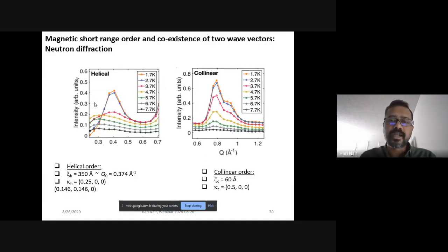So this is a clearer depiction of those two different wave vectors. A wave vector would only indicate what type of ordering you have. If you have a helical ordering, that corresponds to a Q0, which is the ordering wave vector of 0.374. And a collinear order has the wave vector half, 0, 0. For the helical, it is 0.25, 0, 0 and 0.146, 0.146, 0. And they have a sort of evolution as a function of temperature.